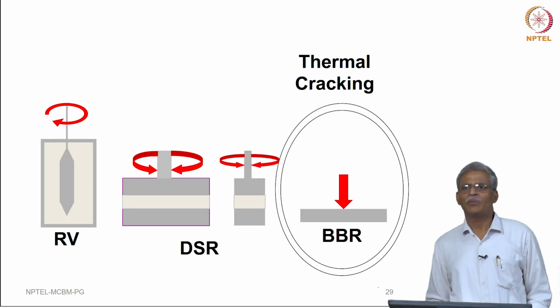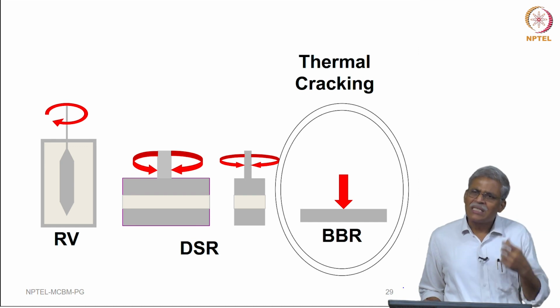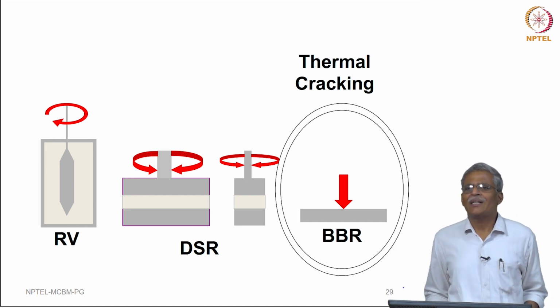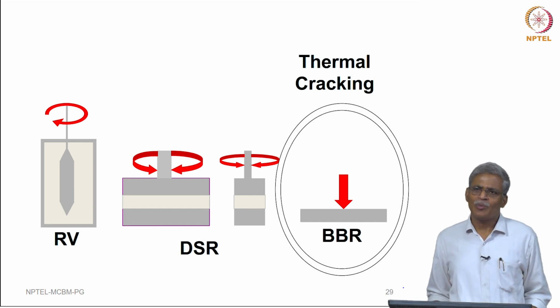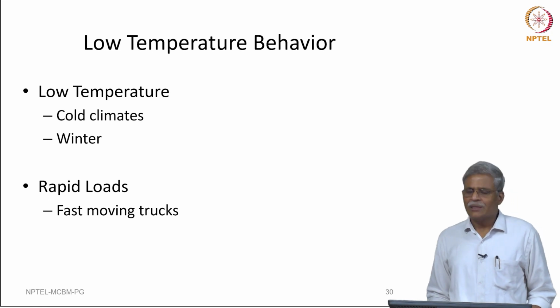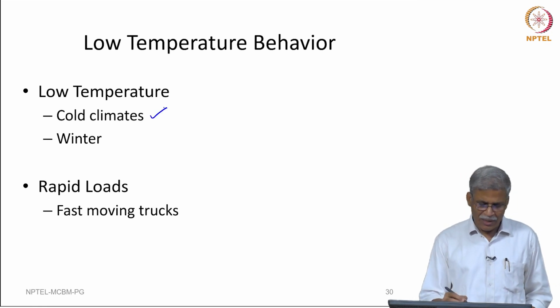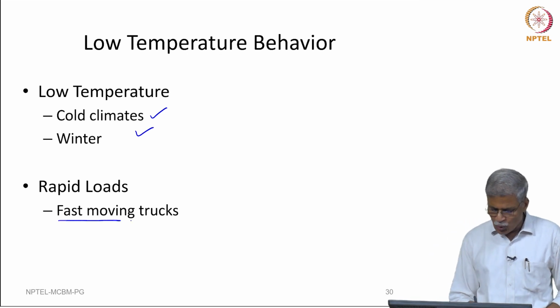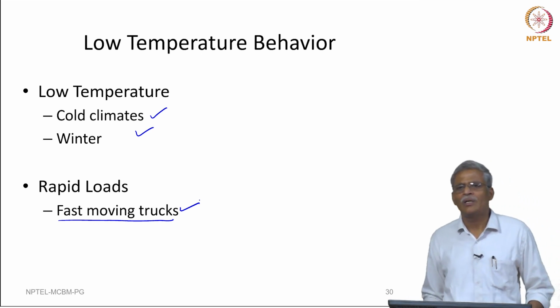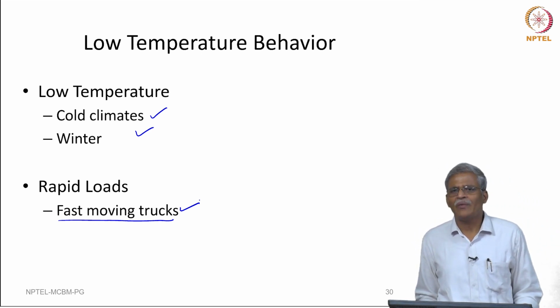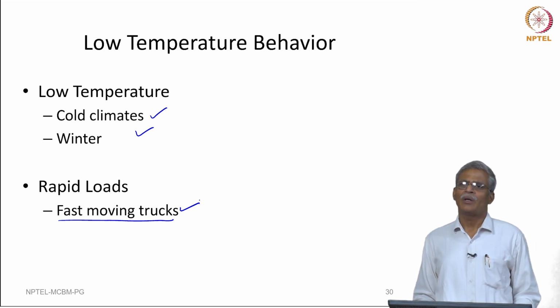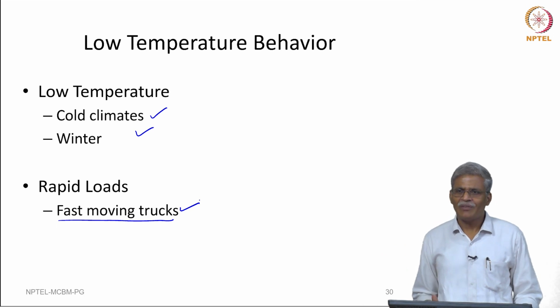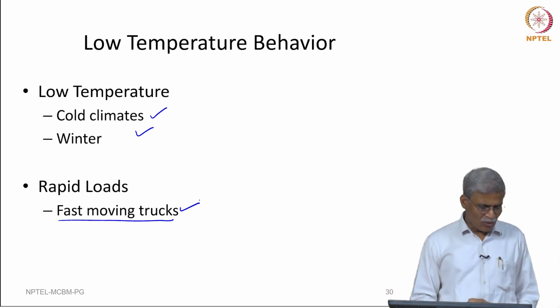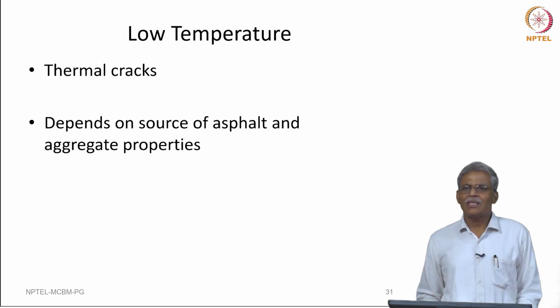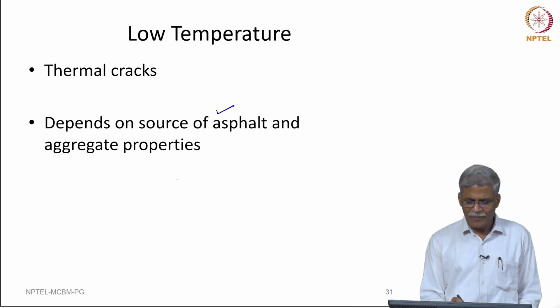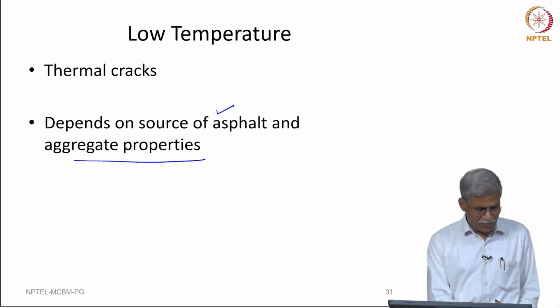Now, finally, we come to thermal cracking. The thermal cracking part is still under development. There are many standards that are being developed, and some of the old standards are also being revised. For instance, the low temperature behavior basically concerns cold climate, winter, and it could also be due to fast moving trucks. In the original low temperature behavior, only the glass transition temperature was taken into account, but when it is coupled with fast moving traffic, the cracking tendency of the pavement also substantially increases. So, these thermal cracks basically depend on the source of the asphalt as well as on the aggregate properties, okay.